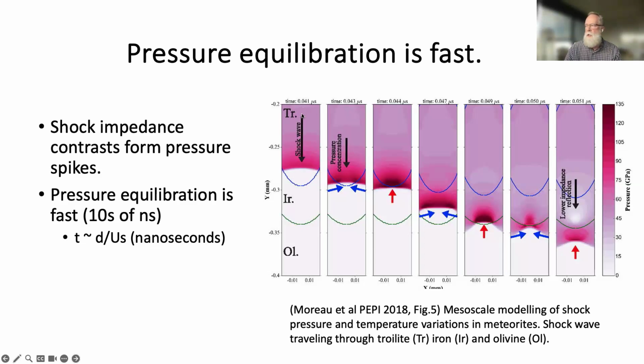So behind the shock front, we've got a pressure on the order of 50 gigapascal. And in front, it's higher. It's maybe 80 or 90. When we hit this interface, it focuses the shock toward the center and produces a spike, a high pressure, high temperature spike. As it passes through and it gets to this other interface, it produces a second spike. And this passes through. And all of this is really important. It generates local pressure temperature excursions, just as Stoeffler had talked about.